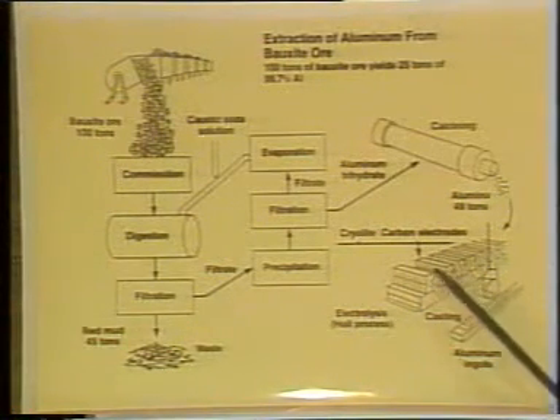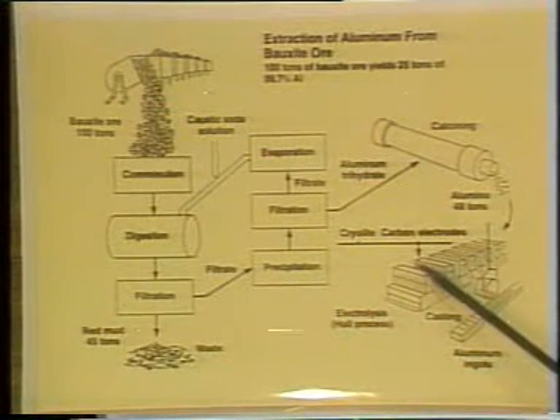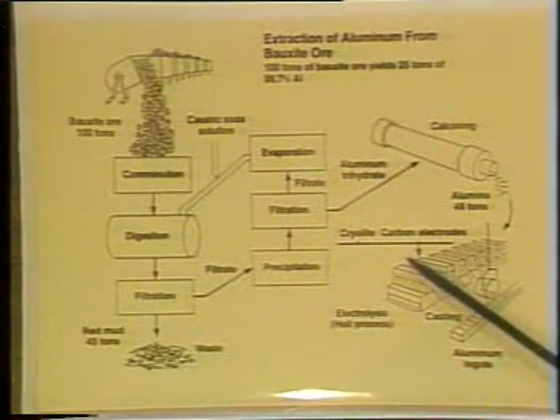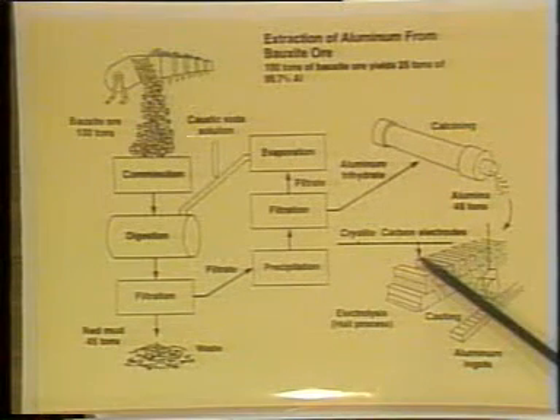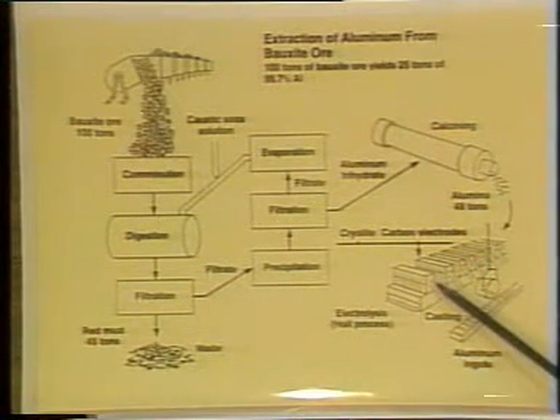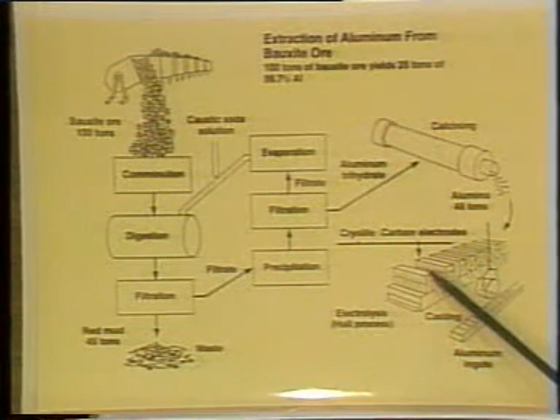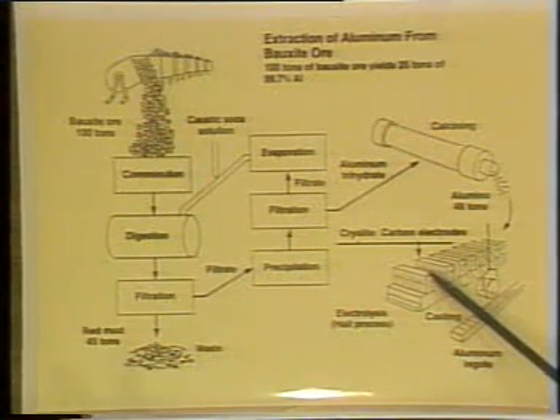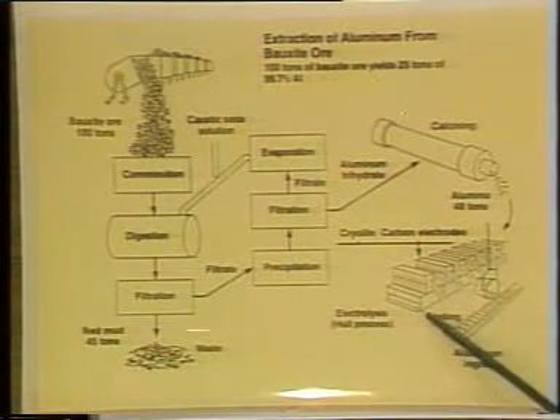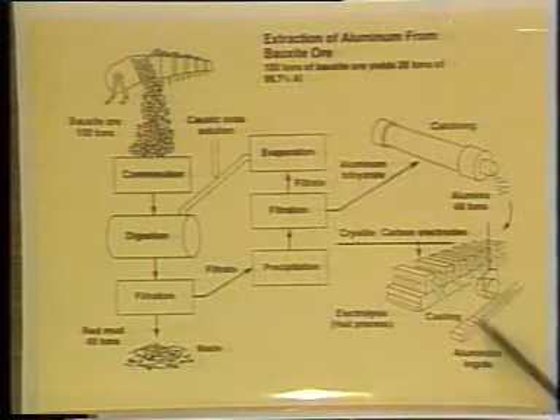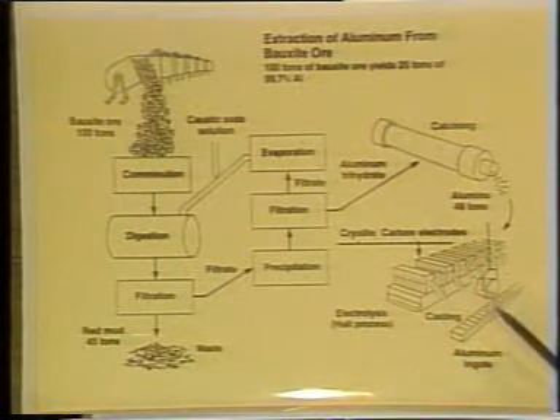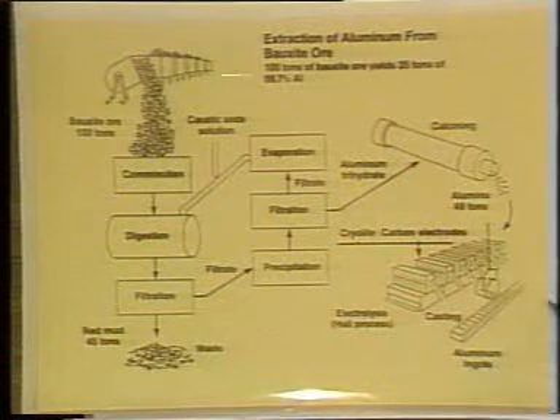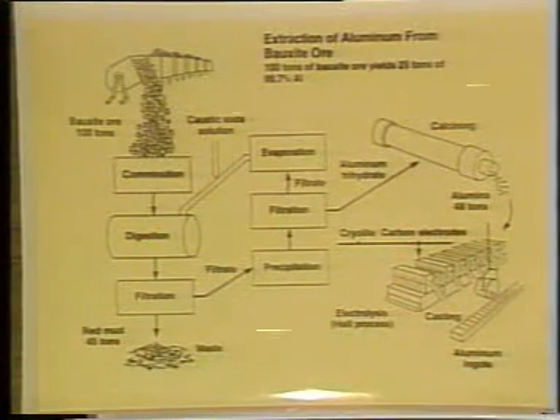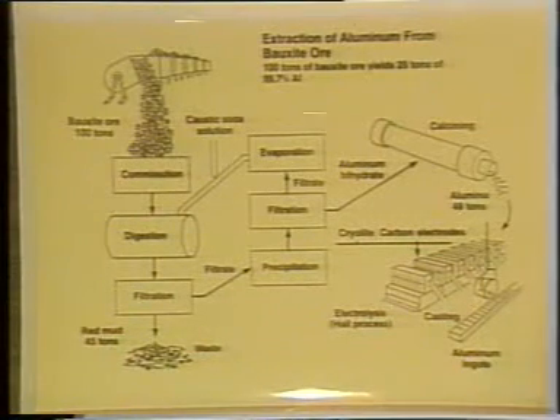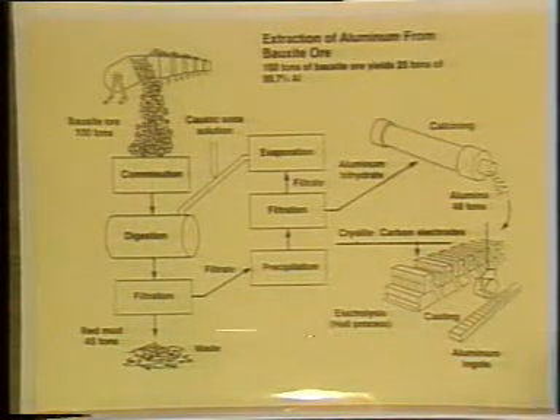And then we can plate out the aluminum electrolytically from this bath that's molten cryolite with the aluminum oxide dissolved in it. And when we do that, then the aluminum falls to the bottom of the pot. The top of the pot, which is a carbon electrode, receives the oxygen when we break up the aluminum oxide, and it burns and supplies some of the energy to keep the pot hot so we can handle the molten aluminum. And we tap out the aluminum, and we are able to cast it in aluminum ingots, or continuously cast it, or make it into powders, or do whatever we want to, roll it into structural shapes. So that's the Hall process, and that's the process that's called the electrolytic process.